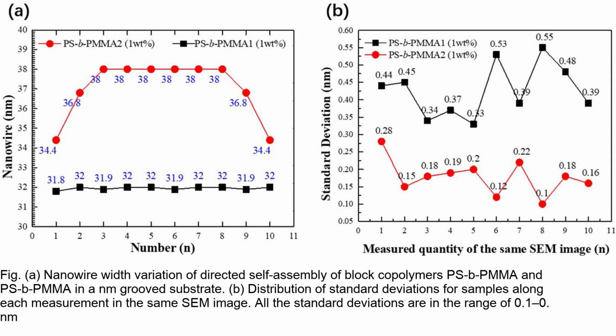The results show defect-free patterns with high resolution and repeatability. The use of specific polymer brushes and control of film thickness are crucial for achieving the desired self-assembly morphology. The DSA process with graphoepitaxy allows for precise directional alignment and parallel alignment of the BCP nanostructures. The results highlight the potential of BCP thin films as pattern templates for nanowire array fabrication in advanced semiconductor devices.